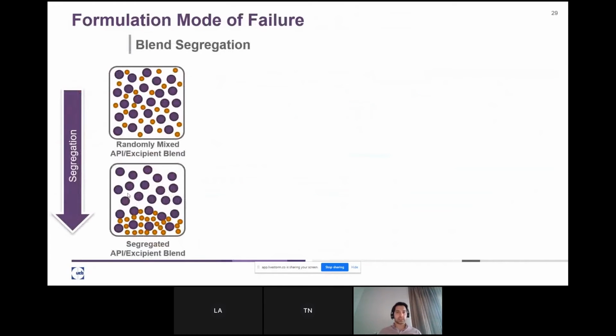So to go into detail on blend segregation, what are we talking about? Here is a binary mixture, for example, which is randomly mixed. As the powder segregates, one of the components goes to one side of the volume, and the rest stays on top. What that causes is that when we do the content uniformity test, the first one passes and the second one fails. So it's very critical to be able to measure that.